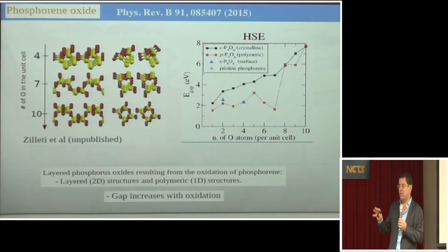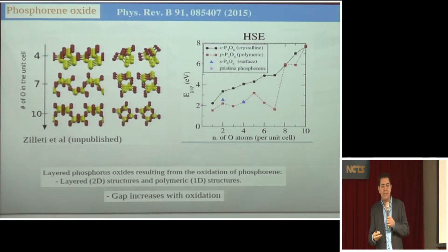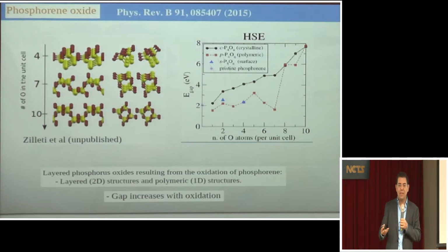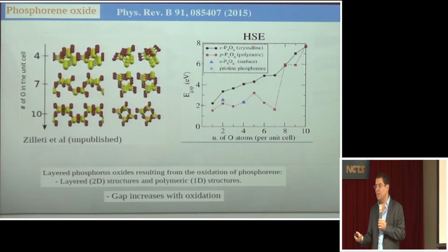If you can oxidize phosphorine in a controllable way, you can extend the gap from, say, 2 volts up to 8 volts. So you can go almost all the way to the X-ray. Okay? So oxygen is not necessarily bad all the time, it's just that you need to understand how to control the oxygen. And it's not an easy atom to control because it's very reactive.